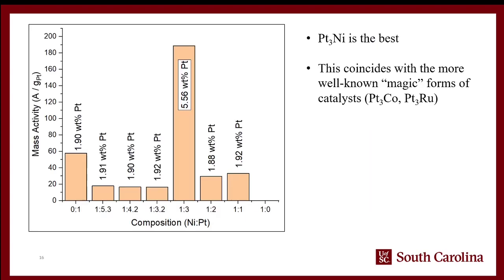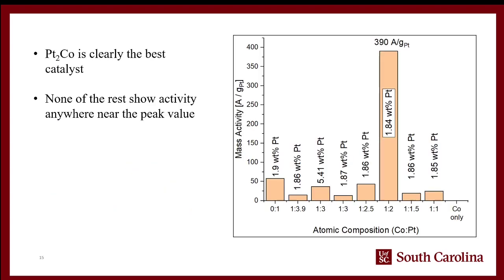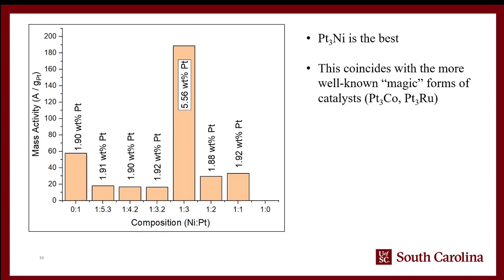Similarly, for nickel, platinum 3 nickel is the best. We kind of see the same thing. It is not as good as the cobalt, which is kind of interesting, but again, we have 1 to 1, 1 to 2, 1 to 3, and 1 to 3.2. The 1 to 3 is very clearly the biggest. Around 190 amps per gram of platinum. For reference, the cobalt was 390 amps per gram of platinum. The cobalt's better, but the nickel is also pretty good.